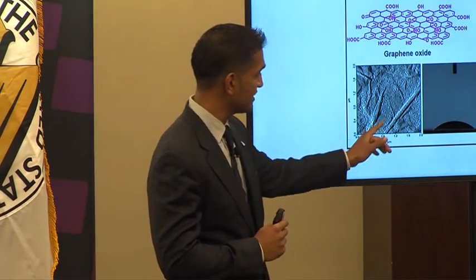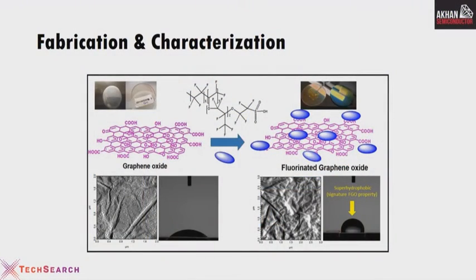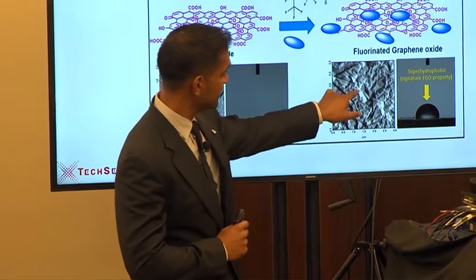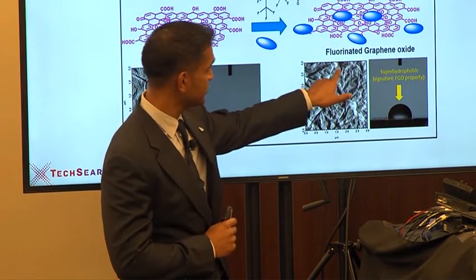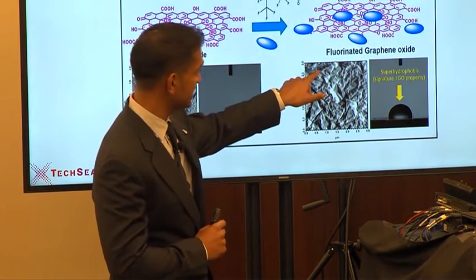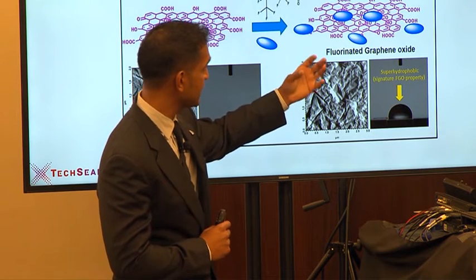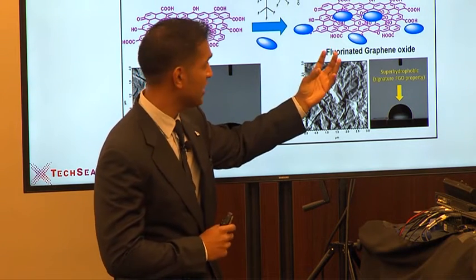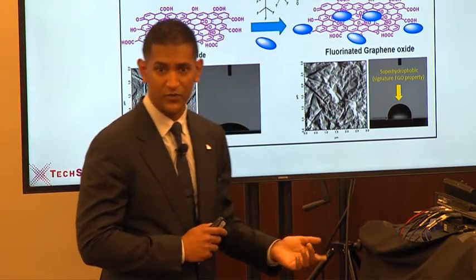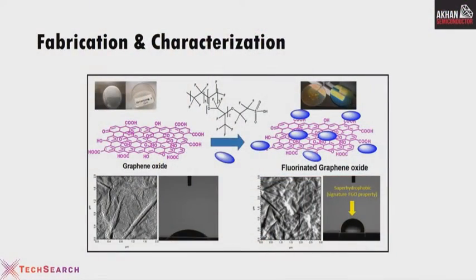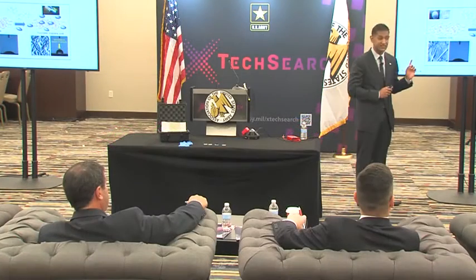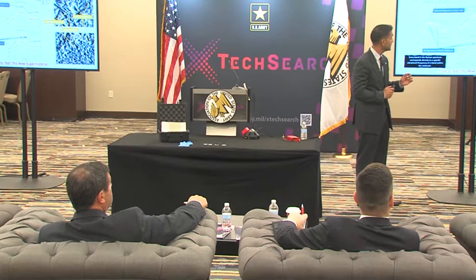You can see the clear ribboning, which is associated with the graphene oxide. You can't see the surface below. This is before the material has been reduced. After it's been reduced, you can clearly see the diamond grains, you can clearly see the graphene oxide, and you can clearly see this two-dimensional sheet of FGO. This two-dimensional sheet is the same thing that causes it to be highly hydrophobic, so the water is actually repelled from the surface. Neat feature in consumer, necessary in military, because this also means it's resistant to oxidation, which means it's appropriate for altitude flight as well as potentially corrosive environments.